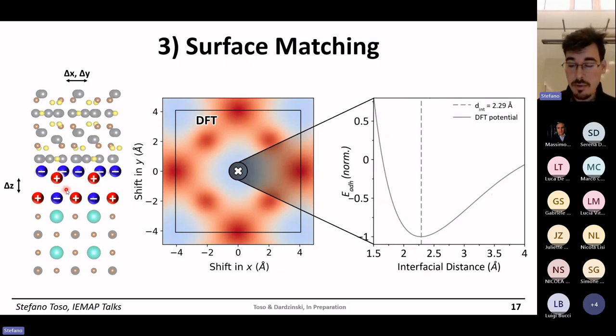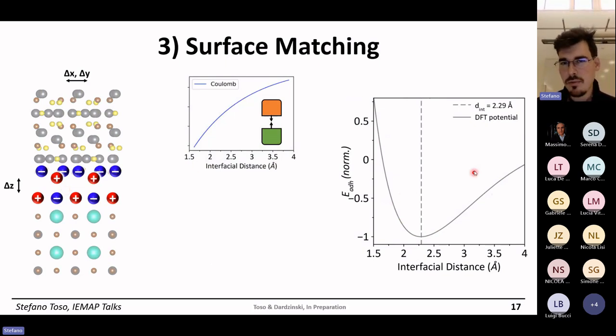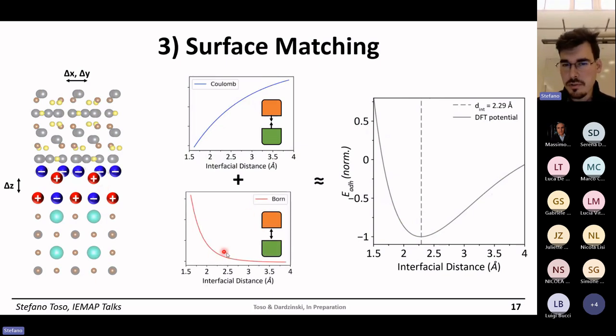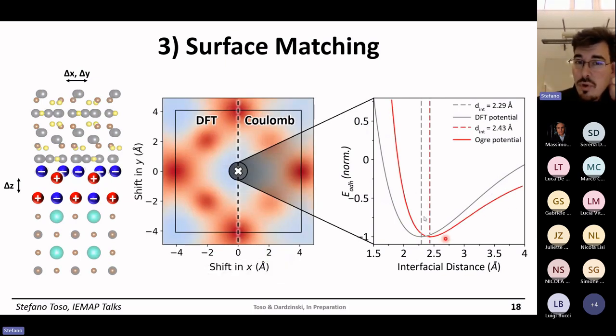The electrostatic potential that we developed is able to describe the same kind of curve by using a Coulomb term that is attractive or repulsive depending on what is on the surface, plus a Born repulsion term that describes the situation where the two atoms are too close to each other and they start repelling due to the electron clouds, right? Now, these two terms together, if correctly parameterized, reproduce quite well the DFT map and also the DFT potential energy surface minimum at a very small fraction of the computational cost. Indeed, all the simulations that I'm going to show you now are performed on my very laptop, and it takes like 2 or 3 minutes per interface. So they're really, really fast.